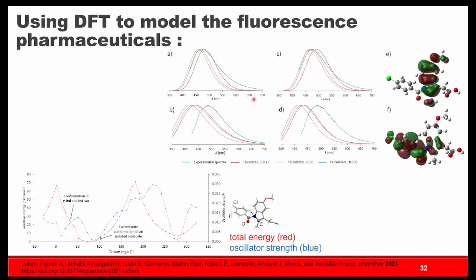I just want to very briefly show, using periodic density functional theory, we're actually able to take the crystal structure and model the fluorescence. So using only spectroscopic measurement, we can really start to get insight into the structure of the materials that we're monitoring. And we're getting quite good agreement with these models here from the HOMO-LUMO transition. The other thing that's really interesting is we can start thinking about what's happening fundamentally. This figure is a little bit complicated, but I'll do my best to explain it. In red here is the total energy, and in blue we have the oscillator strength. What we're looking at here is this dihedral angle.